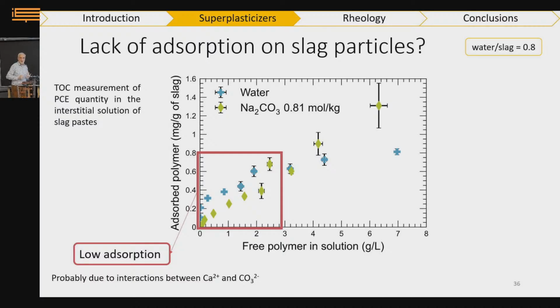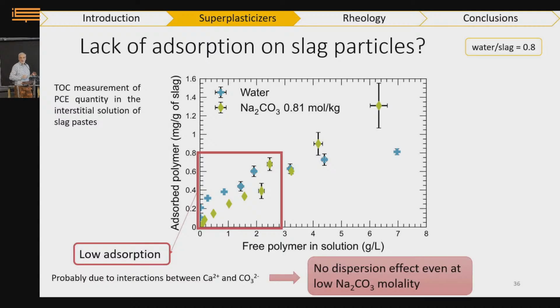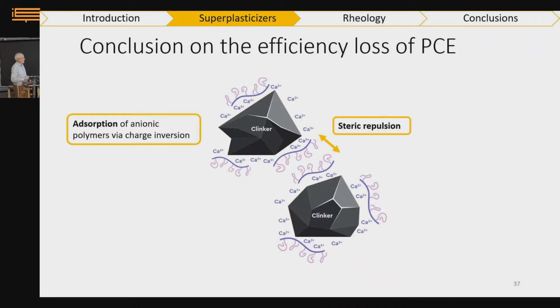It's purely speculative, okay, but it's not shocking, let's say, that carbonates have this effect on adsorption, an effect that hydroxide would not have, and that we didn't see on hydroxides. So here the situation is more complex. We have at the same time the shrinking of the polymer and reduced adsorption, okay?